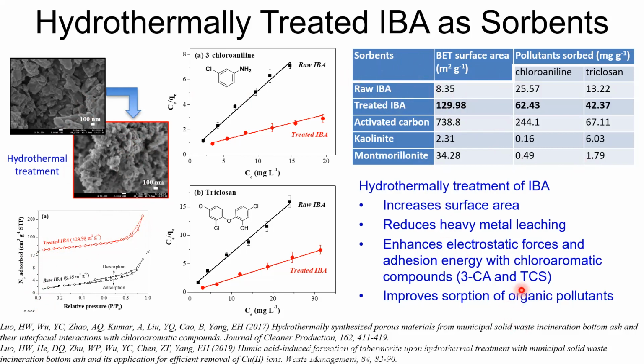We also studied the pollutant absorption capacity. Because of the increased surface area and reduced heavy metal leaching, it enhanced the electrostatic forces and the bonding with 3-chloroaniline and triclosan, and therefore improved the absorption of organic pollutants.